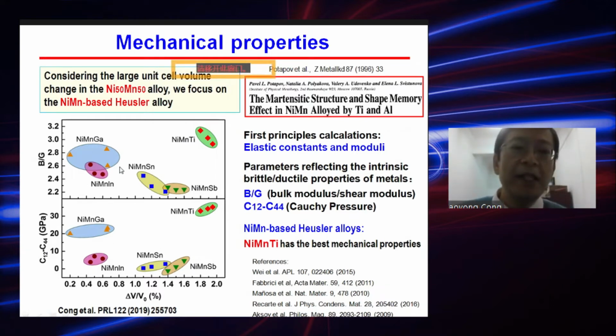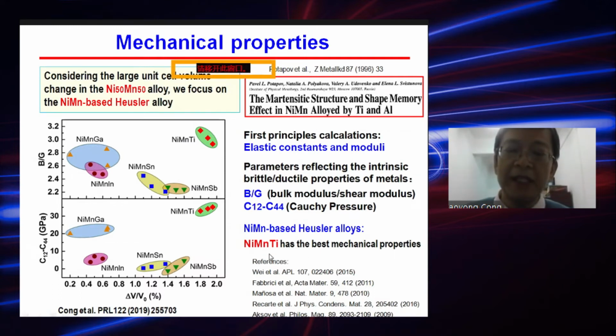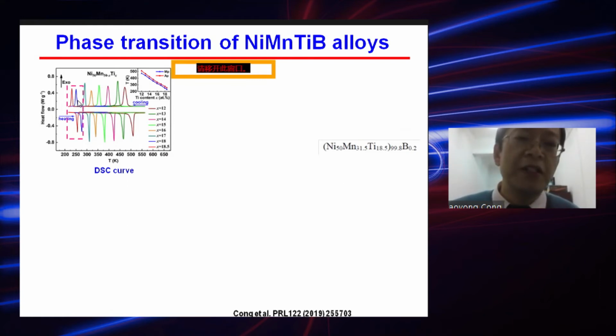We find that among this nickel-manganese-based alloy system, the nickel-manganese-titanium has both the largest B over G and the largest Cauchy pressure. Therefore, it is most probable that the best mechanical properties are in the nickel-manganese-titanium family. Thus, we prepared a series of nickel-manganese-titanium alloys with the titanium substituting manganese. We find that with the increasing amount of titanium, the phase transition temperature decreases. Because we want to get the elastocaloric effect at room temperature, we mainly focus on the alloys with transition temperature slightly below room temperature.